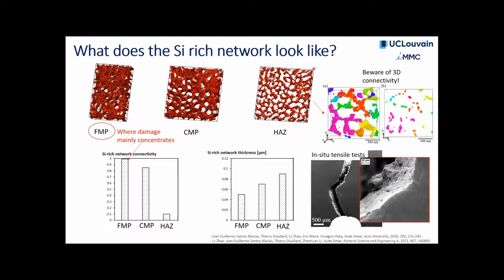And what happens in the heat affected zone? Some people are mentioning damage in the heat affected zone. Well, that can possibly happen if it's a very wide zone. In our case, it was a very small zone. We did have some localization of deformation and some cases of failure in that location in an in situ tensile test. But this was not the main condition of failure. It was mainly in the fine melt pool zone due to this high connectivity of the network.